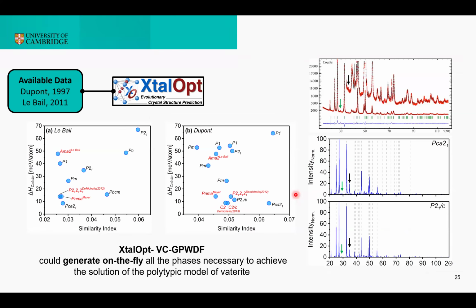So I found two data sets that I could use for microstructure predictions. One was an experiment done by DuPont in 1997 and another one by Le Bail in 2011. Using the Le Bail dataset, I could find an Ama2 structure that seems to be the best fit. So here I have the similarity index and here the enthalpy. Which was not surprising because this was also the structure that was proposed by Le Bail, and this dataset was constituted only by the indexed peaks.